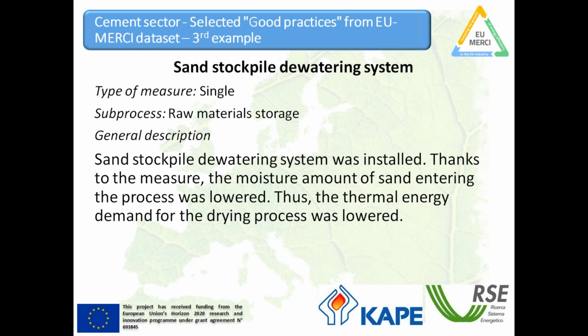The next measure, which I want to show you, is a very simple one, and is still connected with sand. The measure is the sand stockpile dewatering system. This is a single measure in the process part called raw material storage. Basically, a sand stockpile dewatering system was installed, and the system reduced the moisture of the sand, thus having a direct influence on the energy requirement of the process.